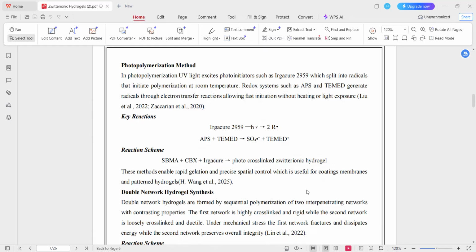control is important. In addition to UV-based systems, redox-initiated polymerization is also widely used. In the redox system, ammonium persulfate reacts with TEMED, which is tetramethylethylenediamine, to generate radicals through an electron transfer mechanism. This approach allows rapid gelation without the need for heating or light, making it suitable for in situ hydrogel formation in biological environments.